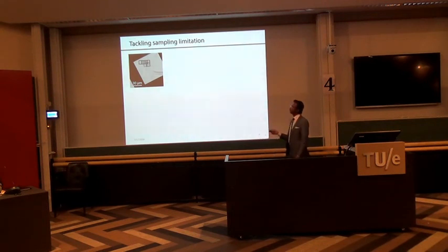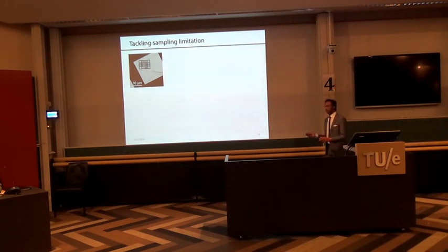The next step in the multi-scale characterization tool is the sampling limitation. Sampling limitation can be tackled by imaging large volumes of data. The large volume can be acquired by imaging thick sections as well as imaging large areas. Large area imaging with a higher resolution can be effectively obtained by automating the image acquisition process. We automated the image acquisition process by moving the stage automatically, which acquires images sequentially, like shown in this figure, with a little overlap, and stitch the images together and obtain the large area map with a high resolution.